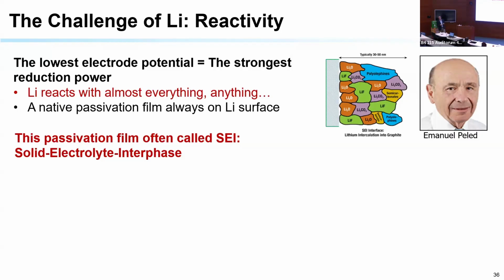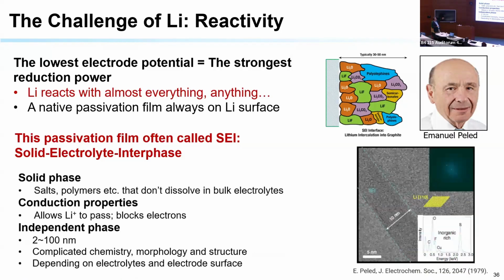So this is the gentleman who discovered the SEI layer. And this is basically in the TEM, you see this layer right here. A very nice layer formed between the lithium metal and the electrolyte. So this layer, as it turns out, is actually crucial for the battery operation. Why? Because if you did not form this layer, the electrolyte would continue to react with the metal and consume it, and then the battery would quickly die. But this layer, which turns out to be conducting of the lithium ions but insulating for the electrons, actually saves the whole battery. Without this layer, we could not have a lithium ion battery.